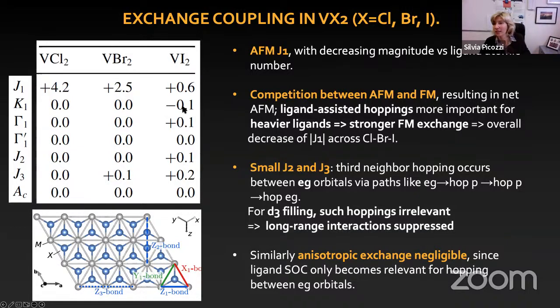And vanadium is also antiferromagnetic, which might be interesting to study because it's probably like a spiral, but you see it's small. Yeah, in the paper we explain basically why it is small, and we conclude that actually it's because of the d3, and it's because of the eg hopping that makes the big contribution to exchange.